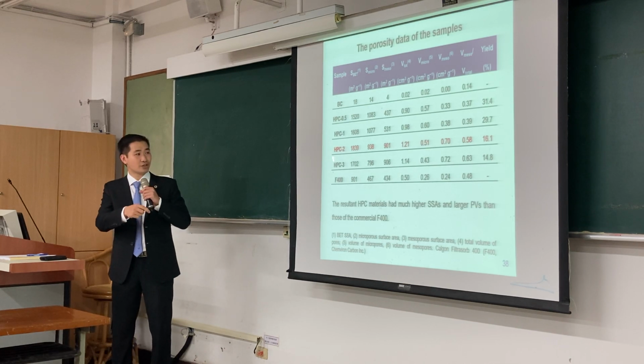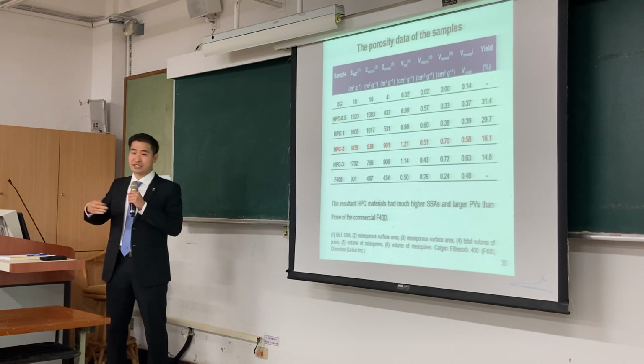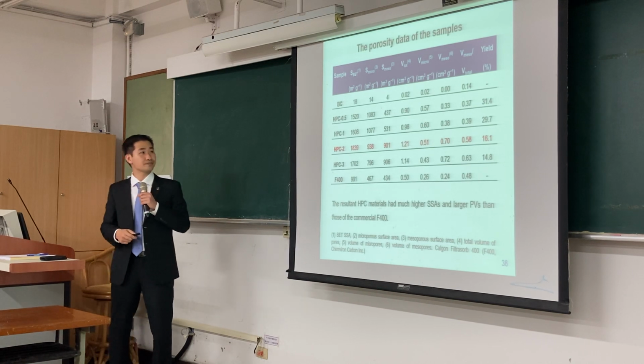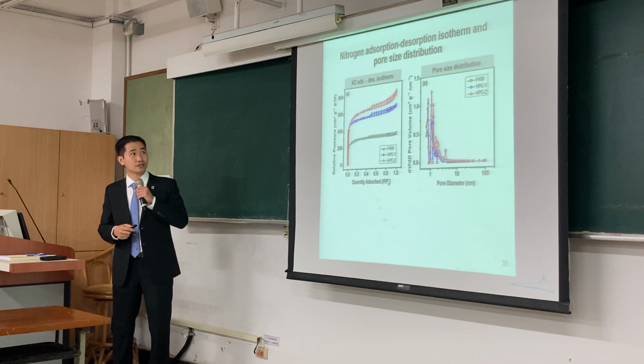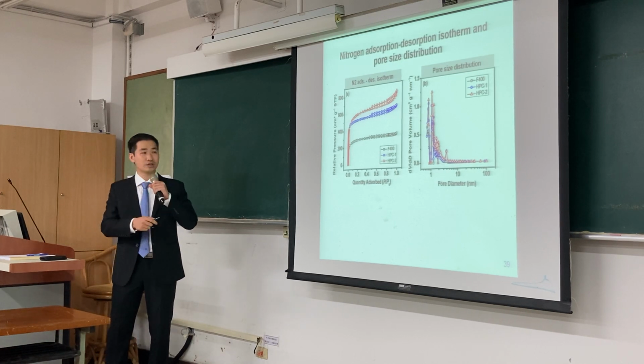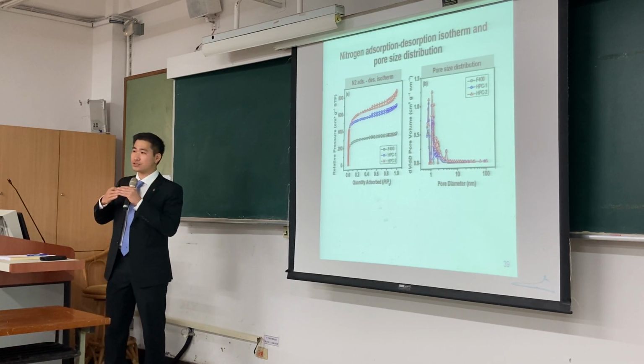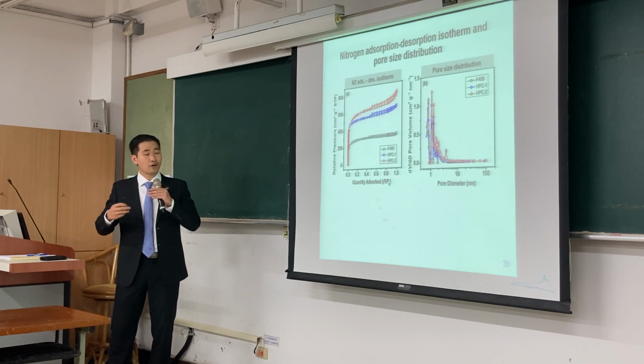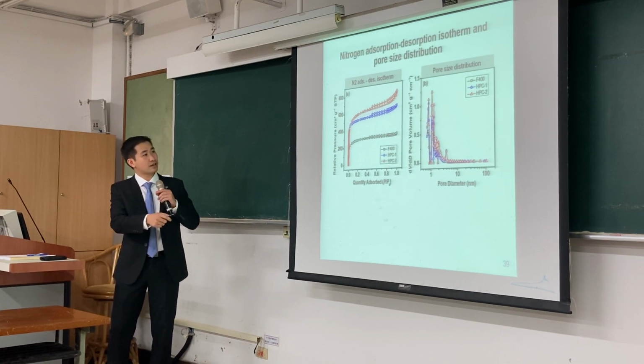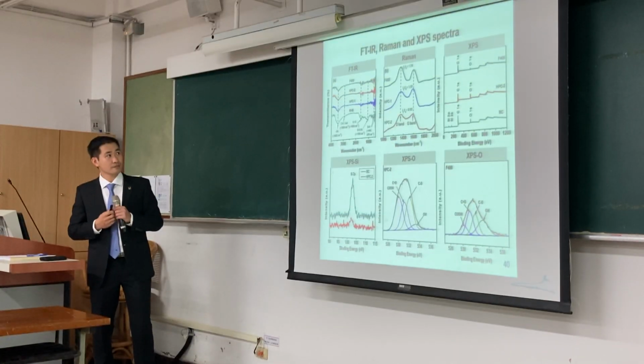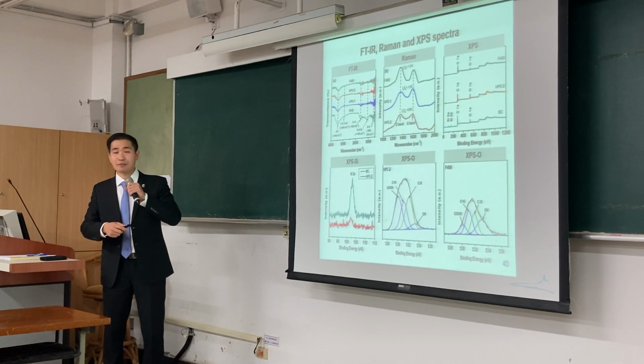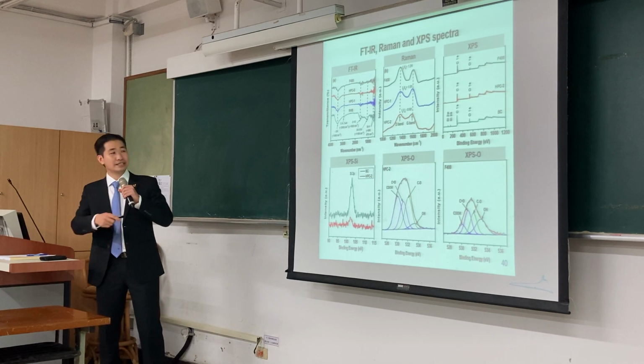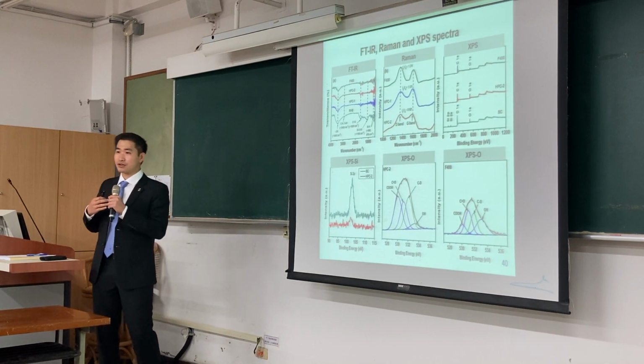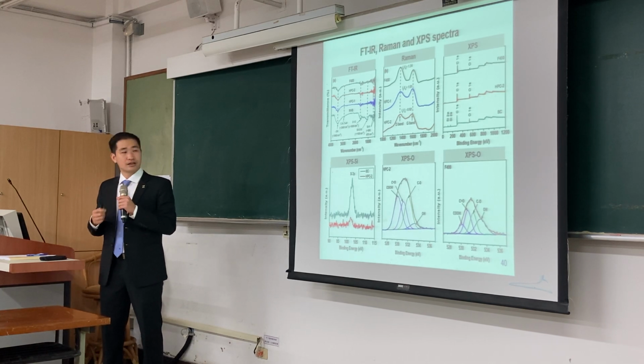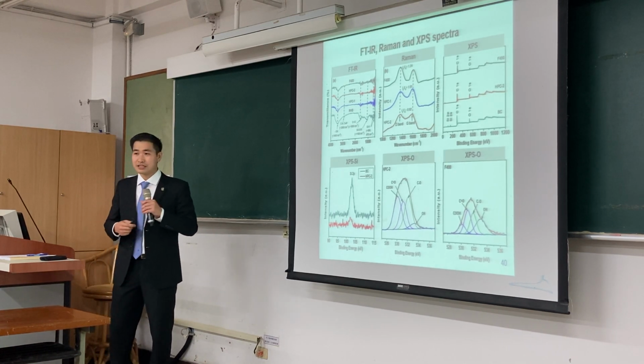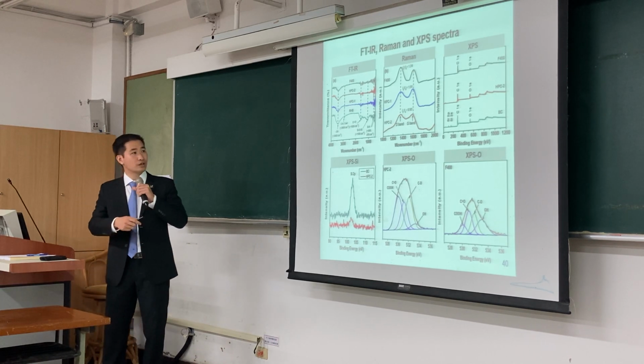Generally, the HPC material has higher specific surface area and pore volume than the commercial material. This is the nitrogen isotherm and pore size distribution of these 3 samples. We collected HPC1 and HPC2 for further investigation and compared them to F400. In the analysis, the results indicate that HPC2 has a higher graphitization degree than the others. It may enhance the electrical conductivity.